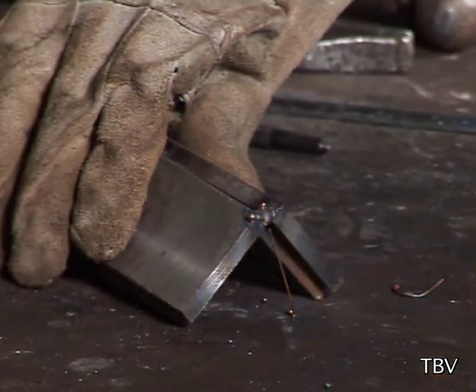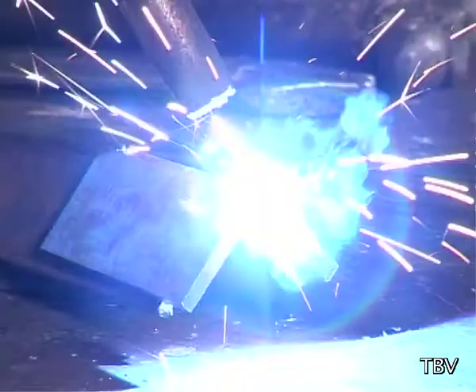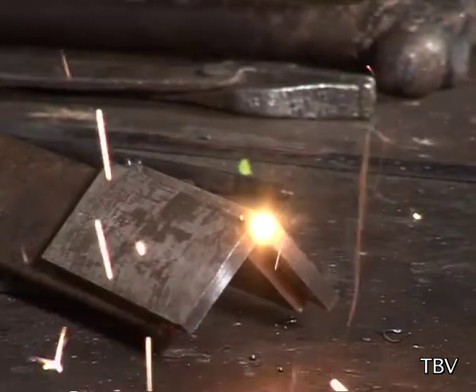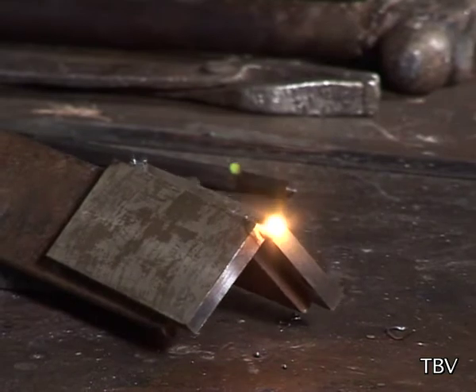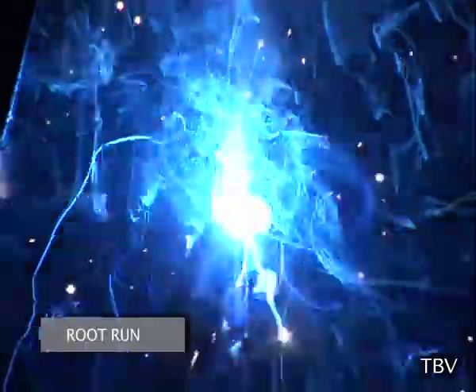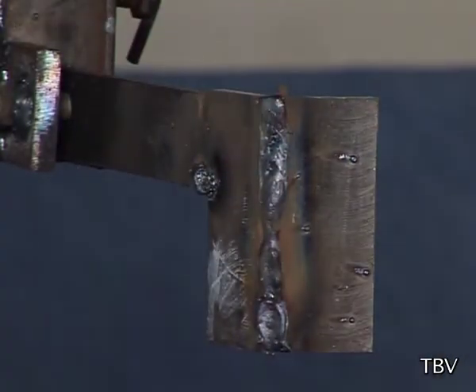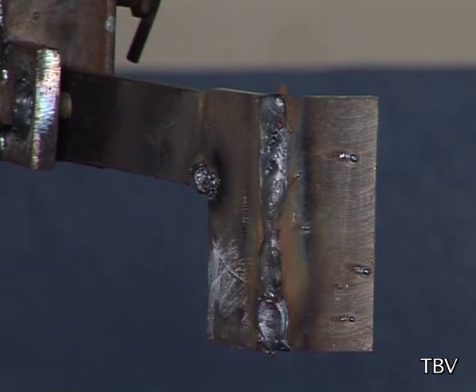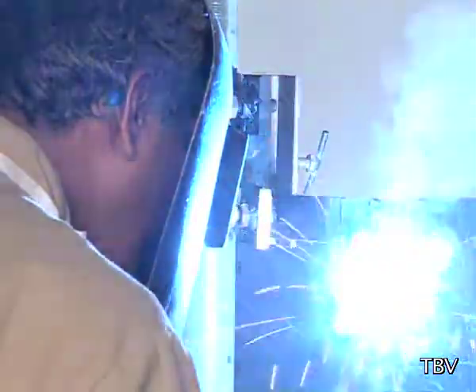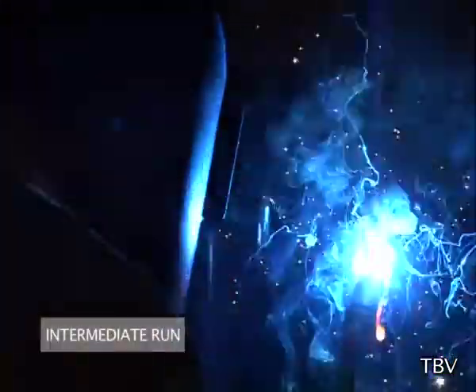Tack weld the jobs. Mount the jobs such that the plate is vertical and the scribed lines are in horizontal position using the job positioner. Hold the gun perpendicular to the joint and strike the arc at the tack. Move the torch from bottom to top end of the joint in vertical position. Maintain the angle of the torch at 10 to 15 degrees towards the direction of travel throughout the weld length.